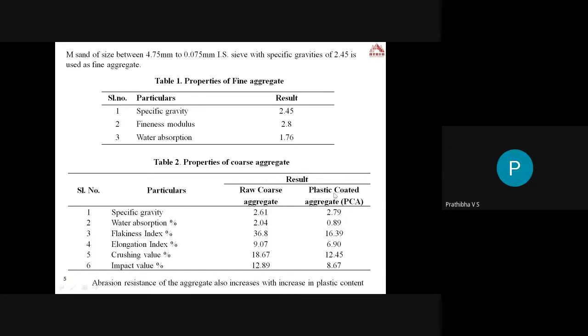Once the plastic is melted, the raw coarse aggregate is added to the melted plastic so that a thin film is formed around the coarse aggregate. After that, a few tests are conducted on both the raw aggregate and the plastic coated aggregate. Here is the comparison between the results.